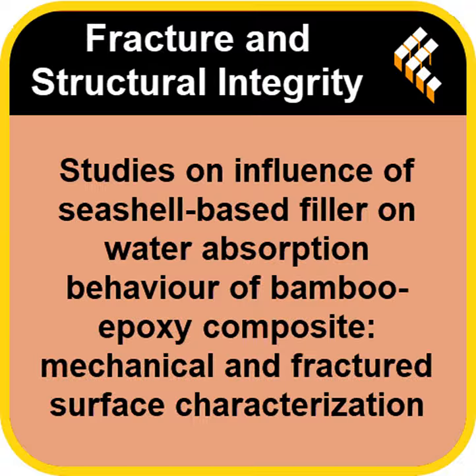Why would that happen? It suggests that at that higher concentration, the filler particles start to clump together. We call it agglomeration. The epoxy just can't wet out and disperse that much powder evenly. And the clumps cause problems. Yeah, these clumps can actually create tiny new voids or weak points at their interfaces, paradoxically giving water new little pathways to sneak in. So 6% was the optimal loading here. Okay, 6% is the magic number.